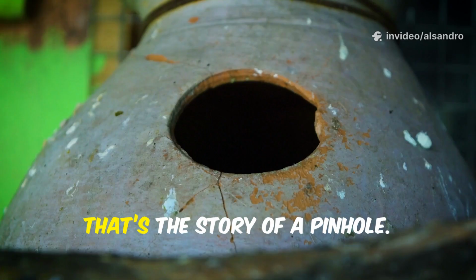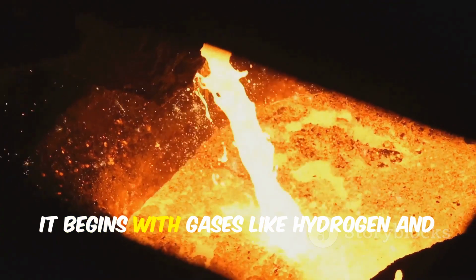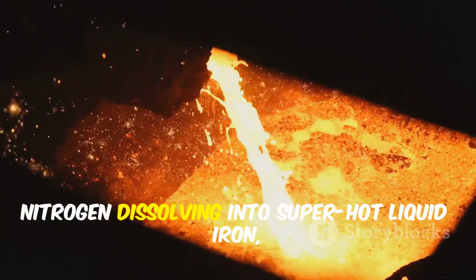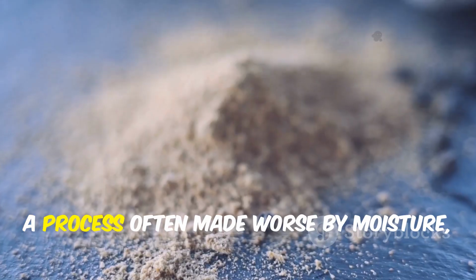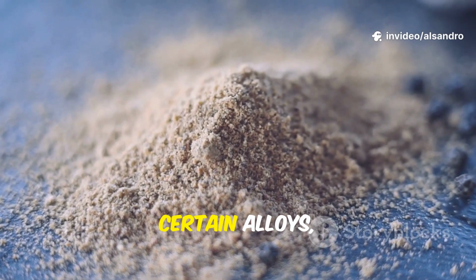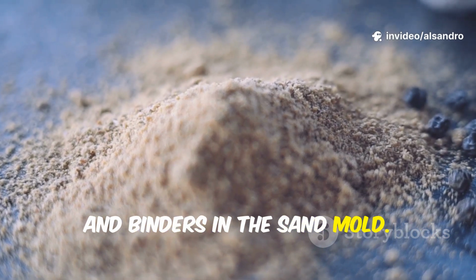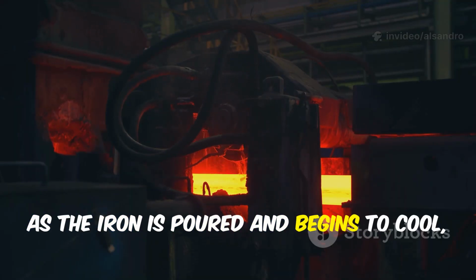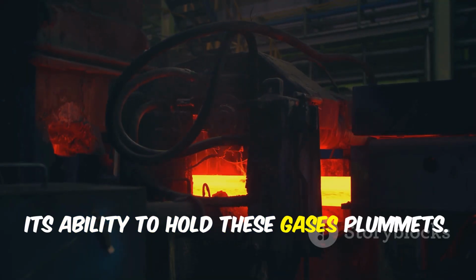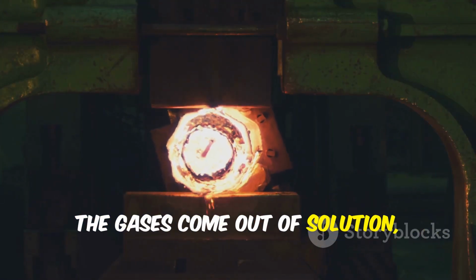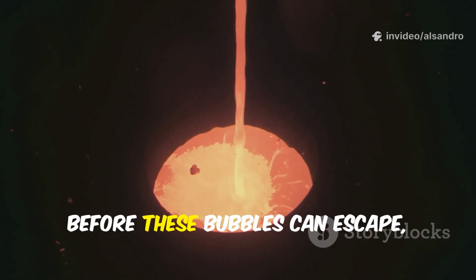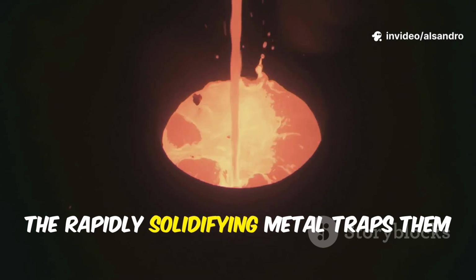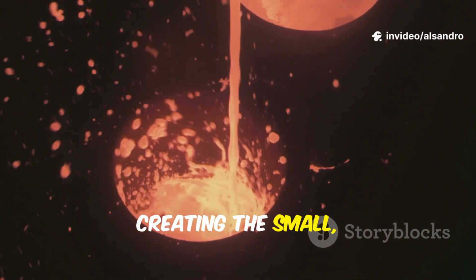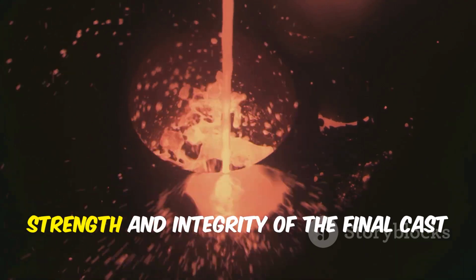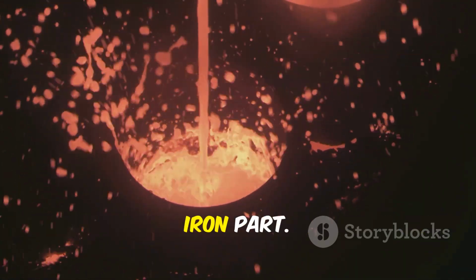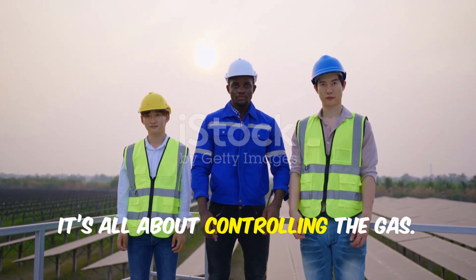And there you have it. That's the story of a pinhole. It begins with gases like hydrogen and nitrogen dissolving into super-hot liquid iron, a process often made worse by moisture, certain alloys, and binders in the sand mold. As the iron is poured and begins to cool, its ability to hold these gases plummets. The gases come out of solution, forming tiny bubbles. Before these bubbles can escape, the rapidly solidifying metal traps them in place, creating the small, round defects that can compromise the strength and integrity of the final cast iron part. Science, it's all about controlling the gas.